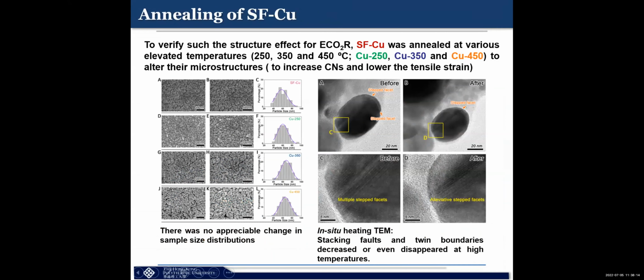So later on, because our as-deposited copper has a pretty good conversion for C2H4, we actually tried to anneal them, to see the annealing effect, because normally the annealing will heal all these stacking faults and increase the coordination number. So that means that if after annealing the catalyst performance becomes poor, then we know that this is a very important factor for the electrocatalytic properties.